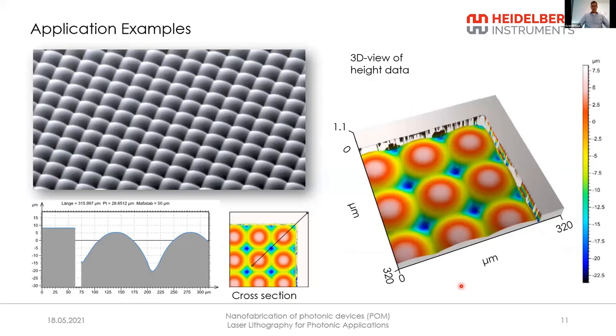The quality of the structure, of course, depends on the system, but the system is generally very reliable and provides very good uniformity across the exposure. The process itself, the development and the resist coating is also very important. This is an example of what can be achieved if everything works together well and the process is tuned well. These are lenses with a thickness of about 25 micron, and we achieved in this case surface roughness across the lenses of less than 5 nanometer RMS. That's without any treatment. It's simply exposed and developed, so there's no reflow or anything. So this is what's possible if everything works well.